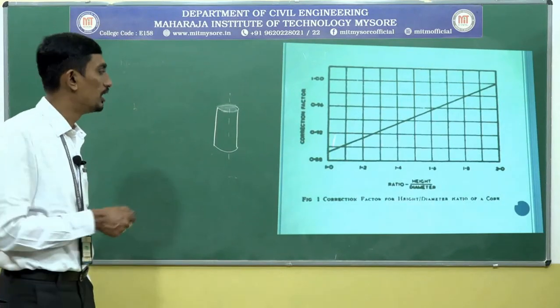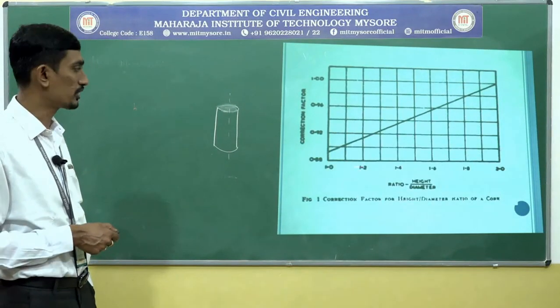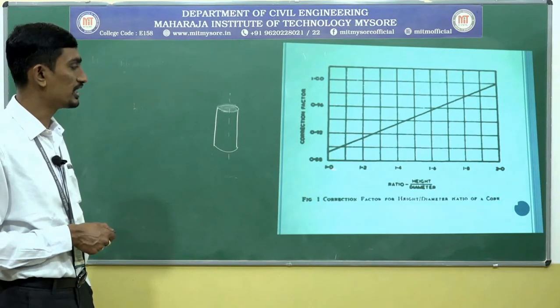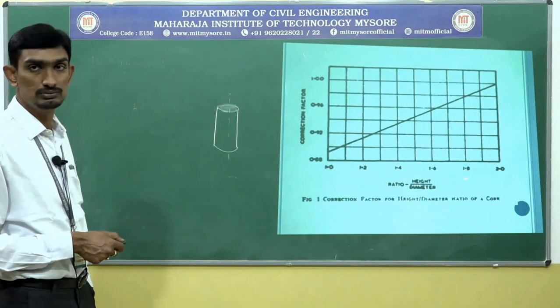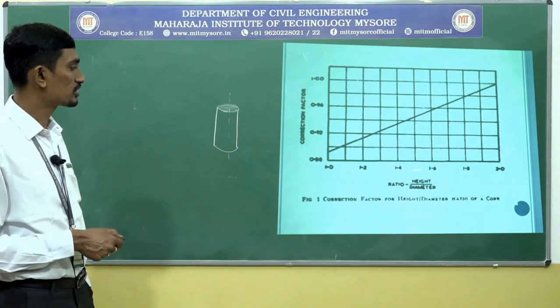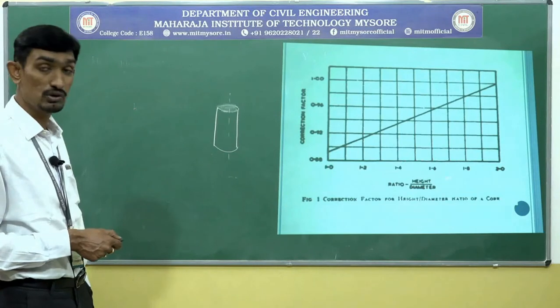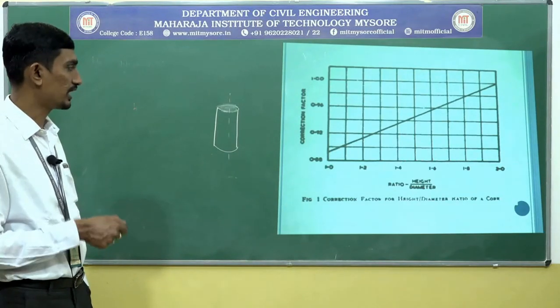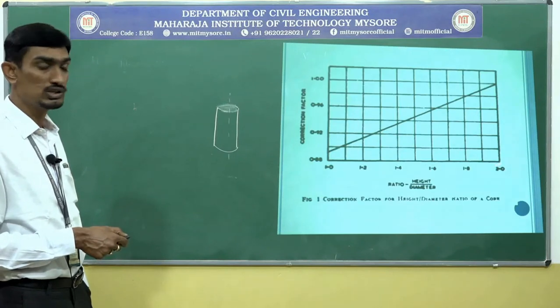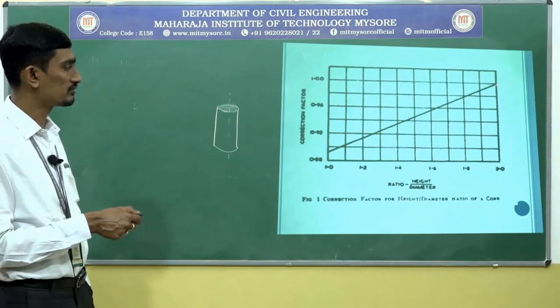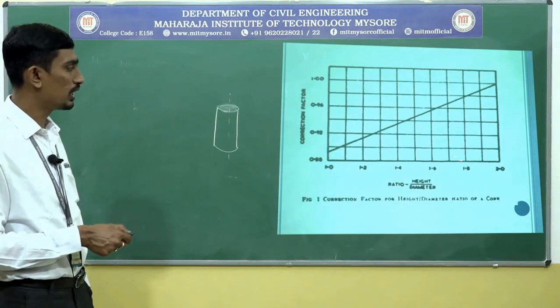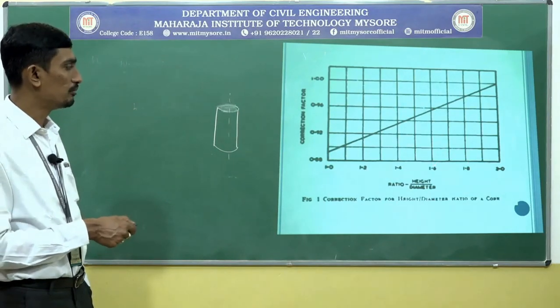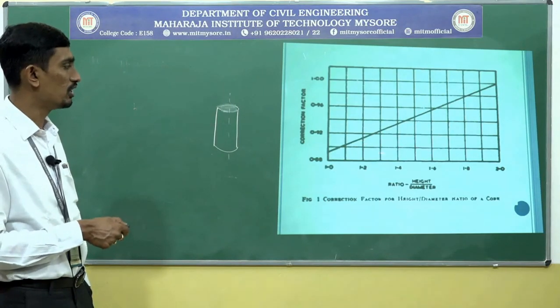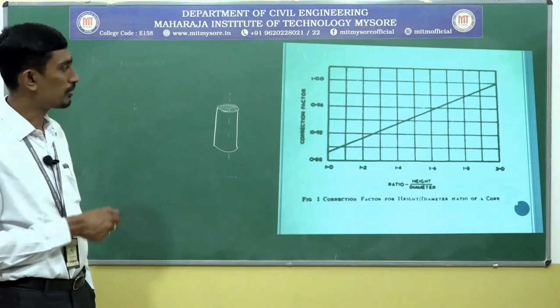So this is the graph which I am going to follow for correction factors. You can see here in the horizontal axis we have H by D. It varies from 1 to 2. Based upon the L by D ratio, you can see the correction factors. For example, if the L by D ratio, or length to diameter ratio, is 2, you can see no correction factor; it is equal to 1. If it is 1, it will have a different correction factor. It will be something else if it is 1.8, 1.6, or 1.5. Based upon the L by D or H by D ratio, you need to take out the correction factor from this particular graph.